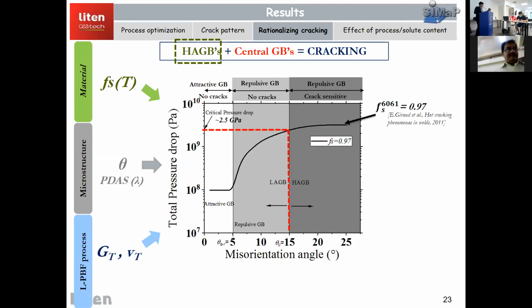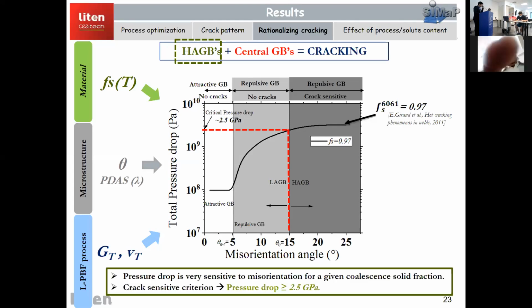So we said, okay, at 15 degrees and corresponding to a solid fraction of 0.97, let's estimate the pressure drop. And this will be the critical pressure drop above which cracking will occur. So we estimated that to be around 2.5 gigapascals. So this is how we estimated that cracking can be sensitive above this critical pressure drop. And pressure drop is also very sensitive to misorientation. So this is how we took into account the high angle grain boundary cracking.